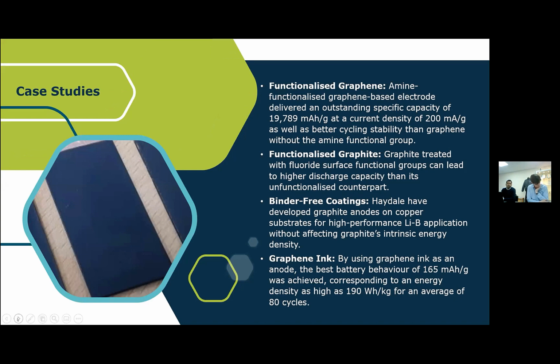Functionalized graphite: we have demonstrated graphite with fluorine functionalities can actually lead to higher discharge capacity compared to the unfunctionalized counterpart. And higher discharge capacity is very important for batteries. So from there, we can learn a lot of things about these kinds of enhanced systems. Currently, we are working on binder-free coatings, just because if we take out binder from the system, we could improve the battery's capacity. At the same time, we could improve the electrical performance as well.